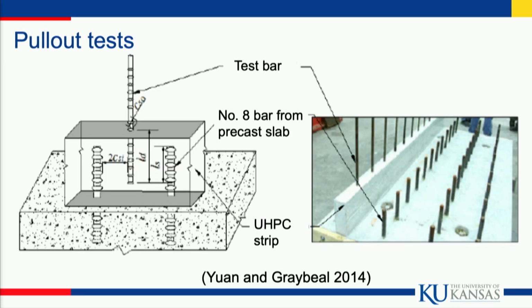Okay, so for pull-out tests, the early work on the proprietary UHPC was done with pull-out tests, Federal Highway. This is a picture from theirs. Notice what you have is a precast slab on the bottom with number 8 bars, 1-inch diameter bars cast into it, and then you cast in the test bar, typically like a number 5, at different spacings and with different splice lengths in a strip that you cast separately after the fact.